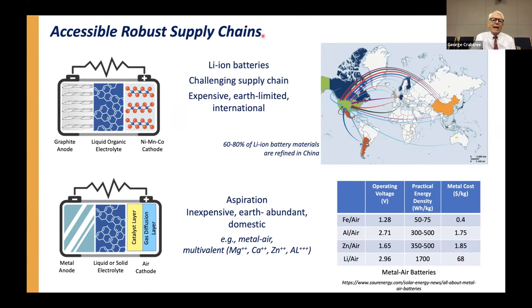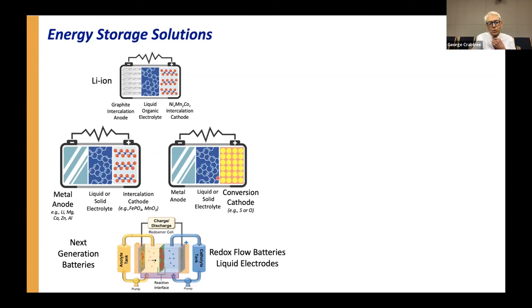How do we do that? As we were saying earlier, you could imagine that some of these batteries with the very favorable supply chains could replace lithium ion in some of the applications that it's used for now, just because lithium ion is too expensive. So what are some of the solutions? And this is a bit technical, but here's lithium ion. It has a graphite intercalation anode. It has a liquid organic electrolyte. And it has an intercalation cathode of transition metals, NMC, which is also an intercalation process. So it's intercalation on both sides, anode and cathode. Well, you could replace graphite with lithium metal.